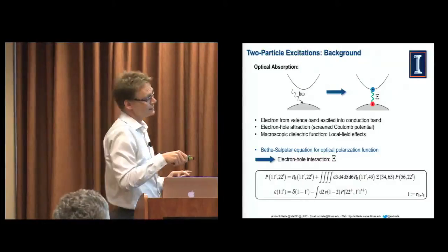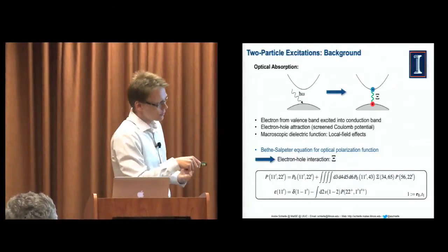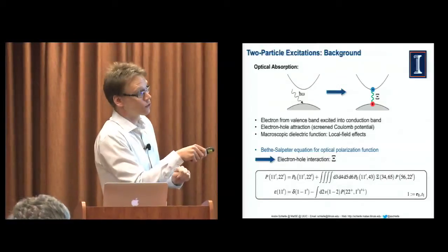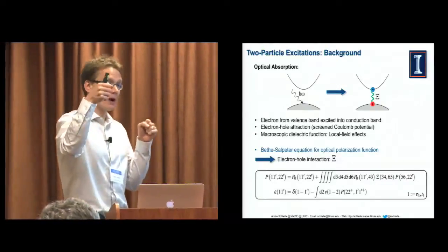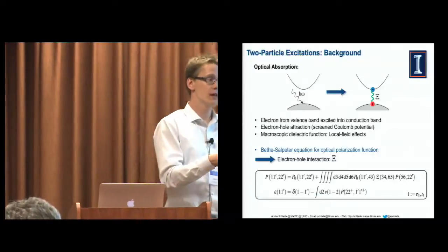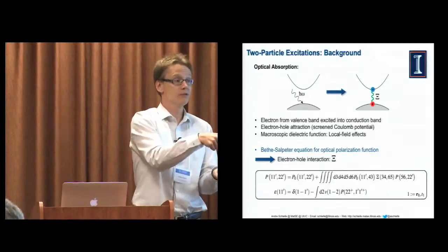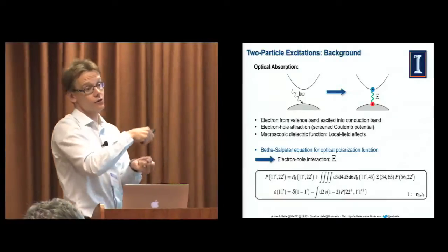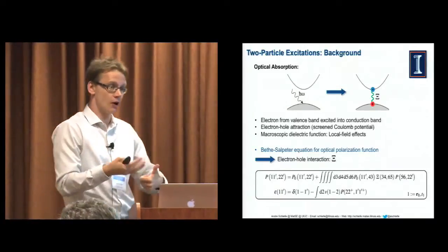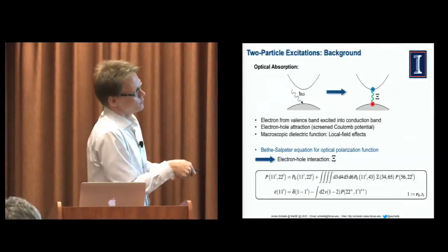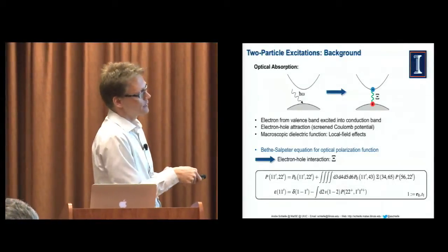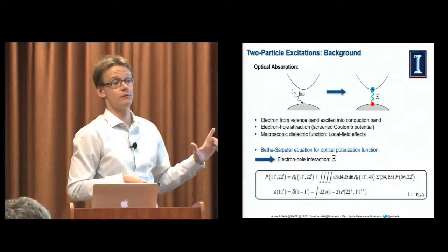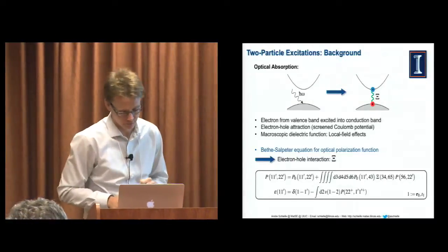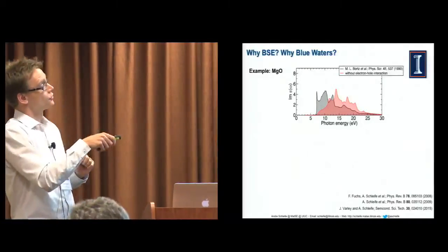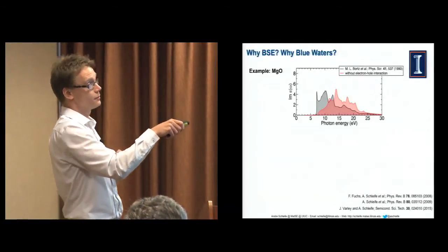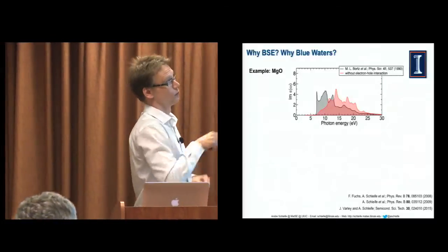So without going into many details, the Bethe-Salpeter equation is an integral equation. The kernel is this screened electron-hole interaction, so it's not just a bare Coulomb potential, but because we're talking about a real material, there is a certain screening just because this all happens in a real material, right? So this electron-hole interaction is screened. That is something we have to also calculate, this screening. Now let's assume we do that, we get this polarization function, then we can calculate a quantity like the dielectric function. This is something that people measure for these materials. I'll show you that on the next slide. Because this next slide actually is meant to show you why we need to do this approach, right? Why do we have to solve this Bethe-Salpeter equation? And that also leads to why do we use Blue Waters.